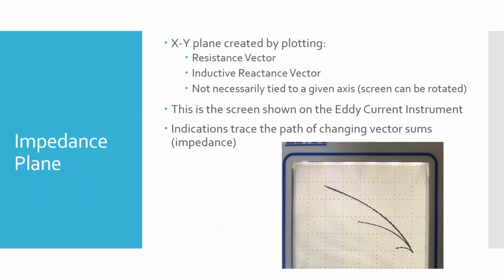But as we go along, if I go across a crack, it causes that inductive reactance and impedance to change. And as it changes, that point moves. And so again, this is graphing that point's position over time. So it draws lines as you continue to move your probe. If you stop at any point, that's where the point stays. But as you continue to move, it'll continue to move.